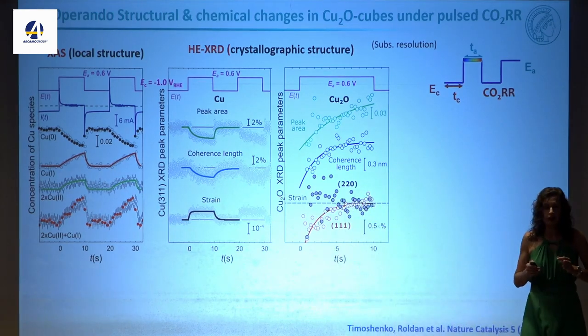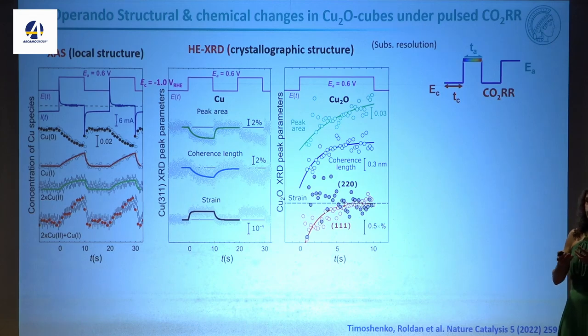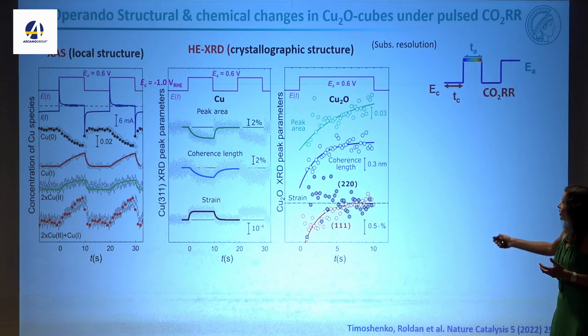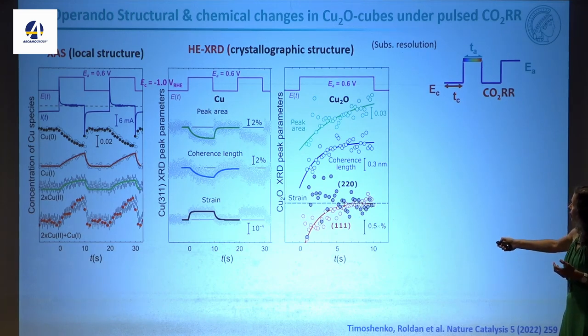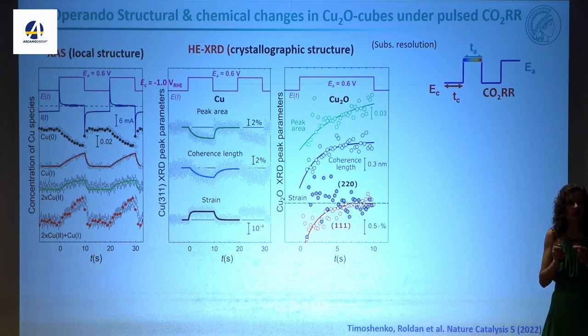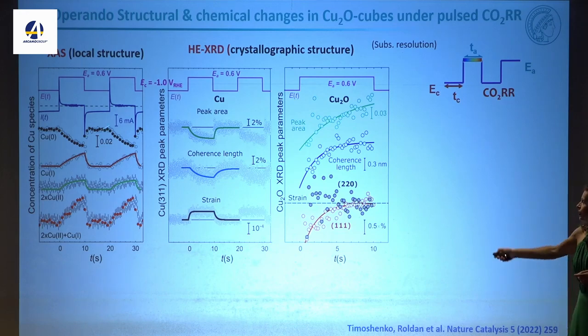But many times people are trying to make conclusions about only XRD data. With the XRD data, I can follow the crystalline phases. For example, these are the XRD data of the metallic copper component and also of the Cu2O that I have under reaction conditions. But once I see it in XRD, it's bulk-like. Here, XAS gives us everything, also the local order, the highly disordered phases. And in catalysis, many times it's these amorphous, highly disordered phases that are actually the active phases. And I wanted to show you that, for example, if you look in XRD at the crystalline phases, we can look during a pulse at the strain that I have on my material.